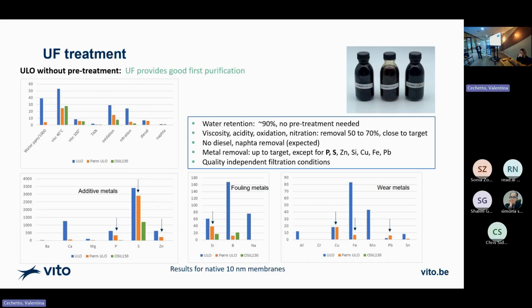Now, how does the retention look like, the purification look like? And we actually found out that UF does a very nice purification step already. You see here in blue the feeds. In orange, you see the UF effect, and in green is where we want to come, the product of the re-refinery. So you see for water content, with this very big open pores UF membrane, we do remove the water. And probably this is because the water is complexed or coupled to some of the impurities there and is actually bigger. And then also viscosity, oxidation level, nitration level, we nicely decrease, coming very close to where we want to be. Of course, diesel, naphtha, we don't remove.